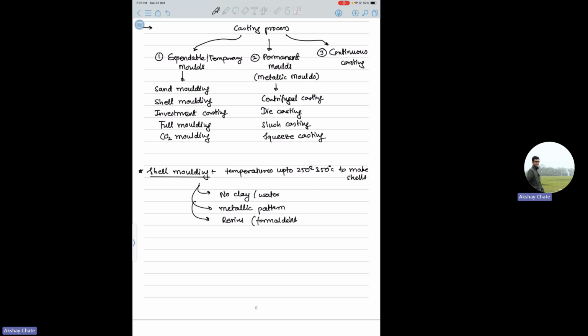They act as thermosetting polymers. The advantage of this kind of method is that you just have a shell. You don't have the whole mold box to fill, and since this shell is usually harder, once your casting is done, you just have to break the shell off the casting, and that's easily possible. But it cannot be used for heavy castings, because the shell also has limited strength. If it's a very huge casting, you cannot do it by shell casting.